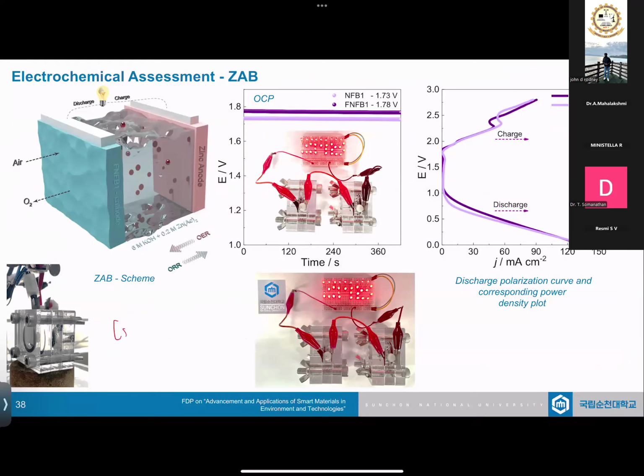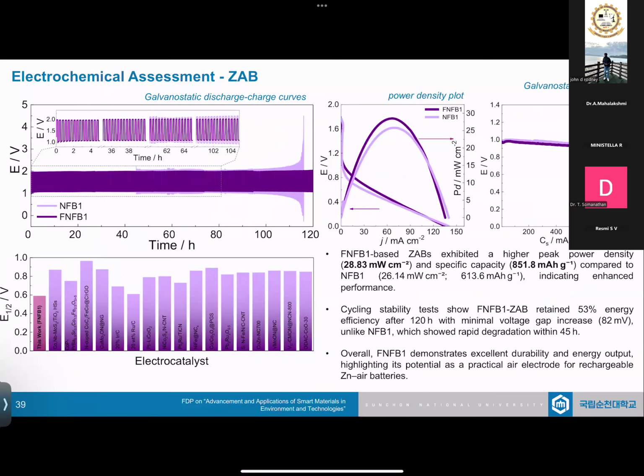So what we did is we did the liquid type ZAB, and it had a very good output. Again, it's not a benchmarking level, but it was able to withstand a good nature. But the main point is fluorine enabling it to work much better. That is proved over here when we did the long-term studies, where the normal NFB electrocatalyst, after, let's say, 40 hours, started degrading slowly. And after around 115 hours, it was destroyed completely. Whereas the fluorine-based structure kept on charging and discharging. Okay, there is loss, but it was stable and it was producing energy. And you can see over here that the galvanostatic discharge was much better just when we brought in fluorine.